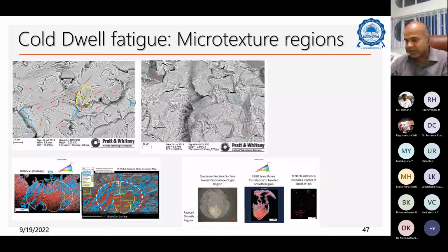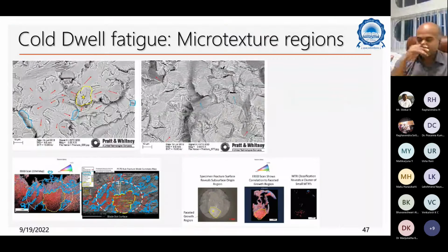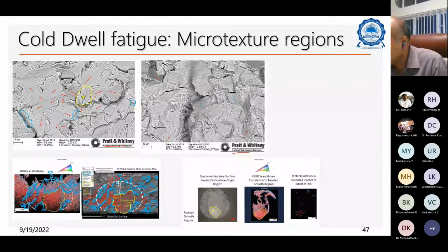So what people have done is some kind of microstructure analysis. As I told, as long as everything is going fine, nobody cares about microstructure, but the moment some failure happens, people dig deeper into the materials issues, because most failures happen because of some uncertainty in the materials. And look at this here. This analysis was done by Pratt and Whitney, which is openly available, and you can see very clear serrations here.